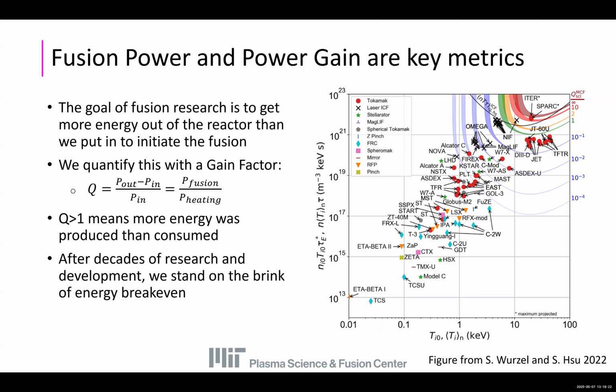If Q is greater than 1, that means more energy was produced than you consumed to actually heat up and produce the plasma. And the point of this plot on the right is just to show that, through the years, we've made a lot of progress towards actually achieving this goal. On this plot in the top right-hand corner, that's Q greater than 1. And you can see all these dots and shapes represent previous fusion experiments and the sort of trend towards high gain regimes. And so now after 6 decades of research on the topic, we're basically right on the brink of energy break-even. At the National Ignition Facility, if you saw Maria's talk on Monday, they've actually already achieved this. And so we know that it's possible to get more energy out than in from these types of reactors. We just need to make it sort of commercially relevant or economically relevant.